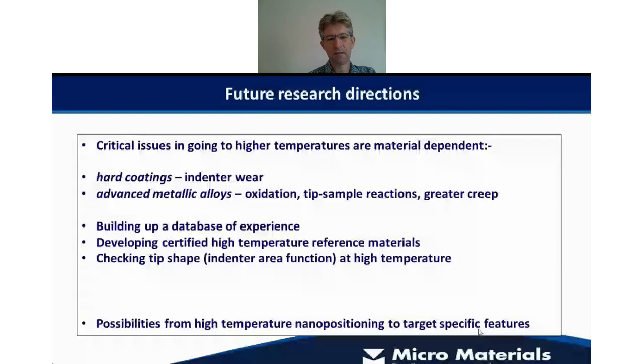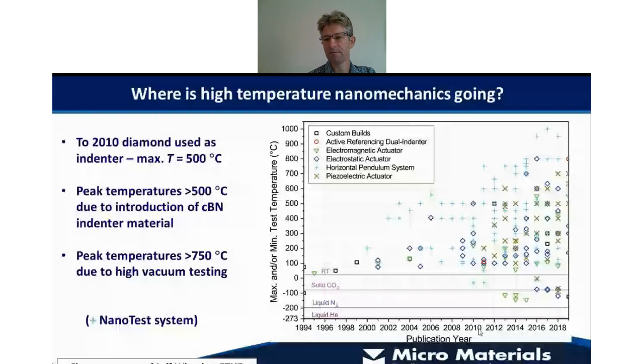And lastly, we can look at doing some clever things with high temperature nanopositioning to target specific features in the material. So before I talk about that, I just thought I'd show this schematic again. Thank you very much to Jeff for this one. It's quite an informative graphic, because it shows essentially the increasing peak temperature with time. And what we can see typically is that up until about 2010, the maximum temperature in these studies was around 500 degrees, because diamond was used as the indenter. But just after that, we introduced CBN indenters that allowed people to reach higher temperatures, up to about 750 or 800 degrees. And since then, we're able to achieve 950 and 1,000 degrees with the testing in high vacuum. In this case, the plus symbols are the Nanotest Extreme and Vantage systems.